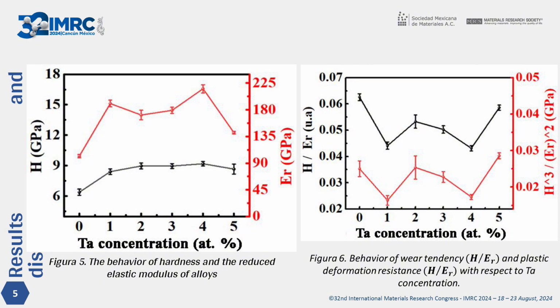In light of the aforementioned criteria, an evaluation of both wear and plastic deformation of the alloys was conducted, as illustrated in Figure 6. The samples with 0, 5, 2, and 3 at percent of tantalum exhibit good wear resistance. This is due to the fact that the elastic modulus is higher than the hardness increments, which results in lower